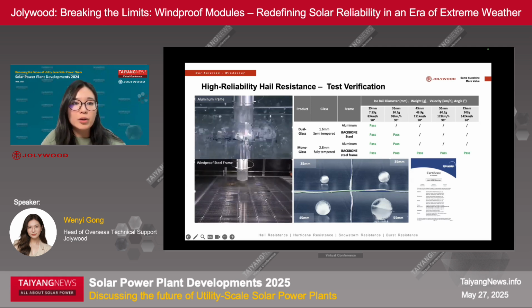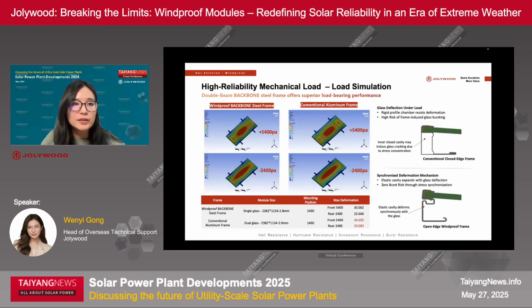It also has a higher mechanical load capability. Here is the simulation result comparing the backbone steel frame and the aluminum. Because of the double beam structure, it can provide more synchronized deformation when the front surface is pressed by external stress, while the closed cavity of the conventional aluminum frame structure will crush the edge of the rear glass and lead to glass breakage. Here there is no such pressing at the backside, so it can help enhance the mechanical load capability a lot.